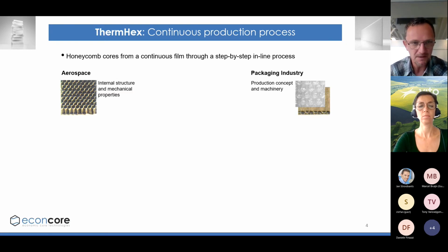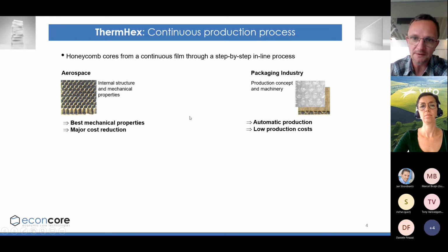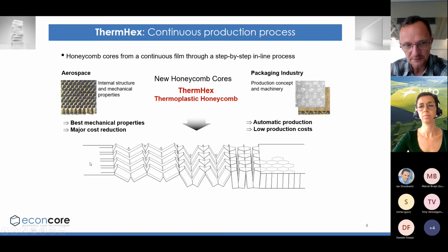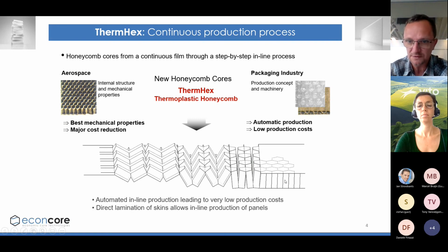But EconCore has taken a little bit different approach to that, and this aerospace honeycomb-like structure has been combined by EconCore with the production principles borrowed from the packaging industry, where automation and low cost is a must. So what we do is extrusion of thermoplastic materials in a thin film that are immediately rotationally converted by vacuum forming into these half hexagons that we fold up into a honeycomb structure. And at that moment in the process, we can end up with a honeycomb core structure, and we do that in many cases. But in fact, the beauty of the technology is that with this continuous production of the honeycomb core, we can laminate skin layers onto this honeycomb core on the fly with an inline integrated process, and that way we can end up with an added value product being a sandwich panel, not just a honeycomb core.